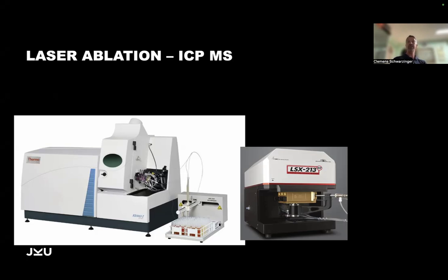ICP stands for inductively coupled plasma. We can have this plasma like we have in the CVD synthesis of the diamonds. It's here in this chamber, and it's like a little sun. It has temperatures up to 10,000 Kelvin, so extremely hot. And if you put anything into such a plasma, it will decompose into atoms and ions. And the ions is what we are using, because here in this left part of the machine, we separate the ions and identify them. What we have on the right side, coupled in our case, is a laser ablation.